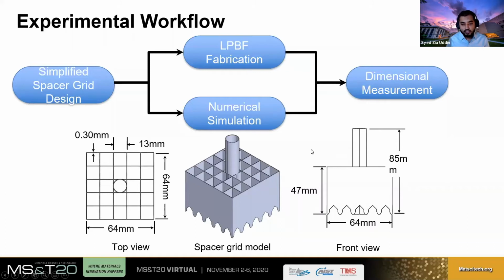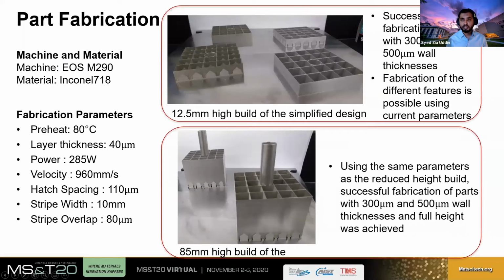For example, in our simplification, we still keep the wall thickness to 300 micron, which is very close to what the original design is. We maintain the height of the spacer grids, which is around 47 millimeter, which is also the actual height of nuclear spacer grids. We preserve the individual cell sizes, and so the only simplifications that we have made here is we have excluded the spring and dimple features from the wall. So in the next slide, we will see the fabricated part.